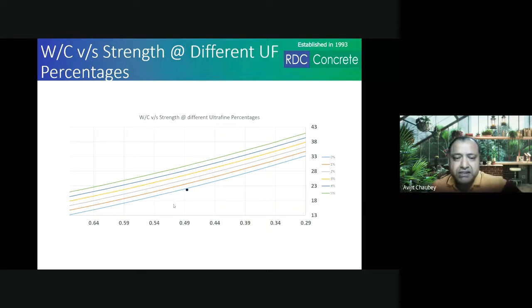So this is what we have tried to do with the water cement ratio and the BRMCA method. We have gone a step ahead. This graph is with respect to the water cement ratio and the strength. So this is what happens with water cement ratio and strength for different percentages of ultrafine: 0%, 1%, 2%, and so on. At 0.39 water cement ratio, let us say you get 27 MPa, and if you incorporate 1% ultrafine as a replacement of cementitious matrix, you tend to get 2 MPa higher. Then at 2%, you get even higher. And this is how we have been able to plot the strength. So this is what I meant by this.